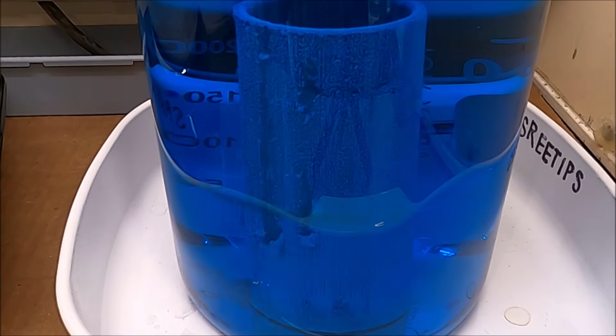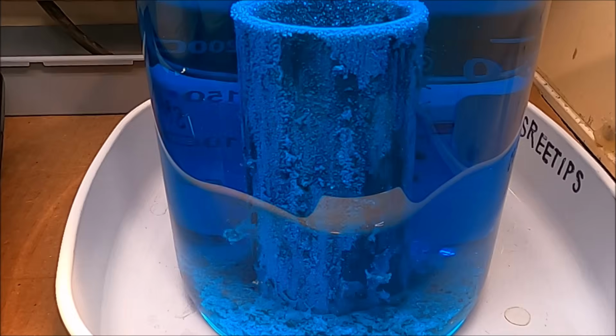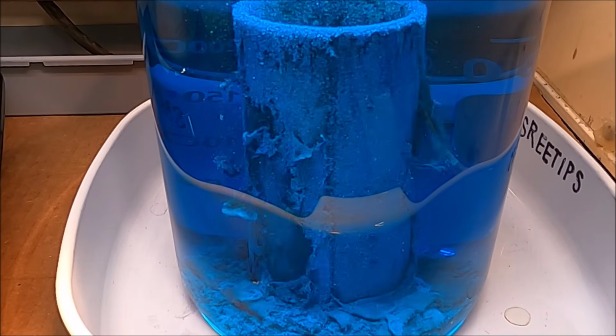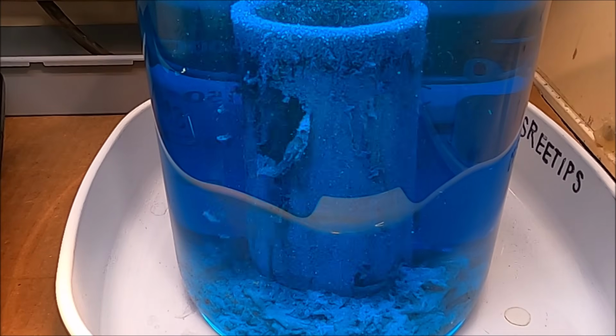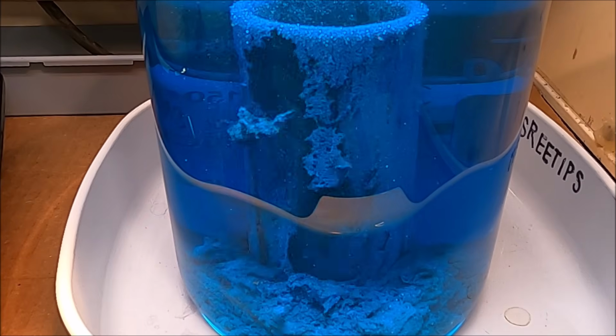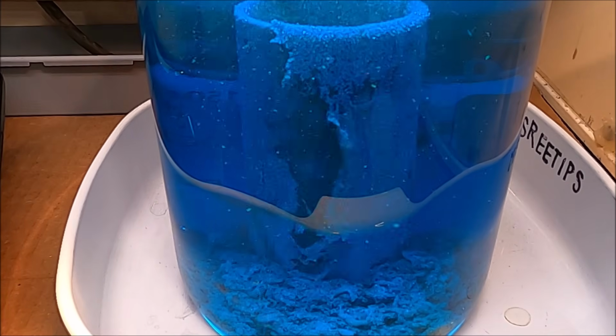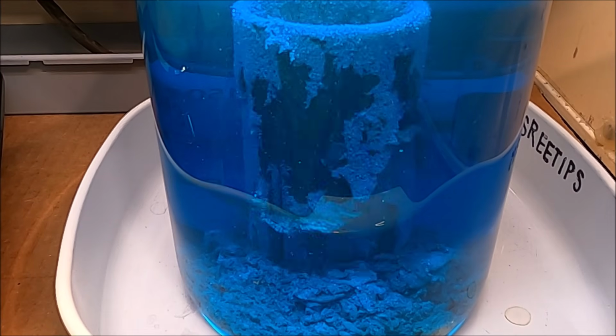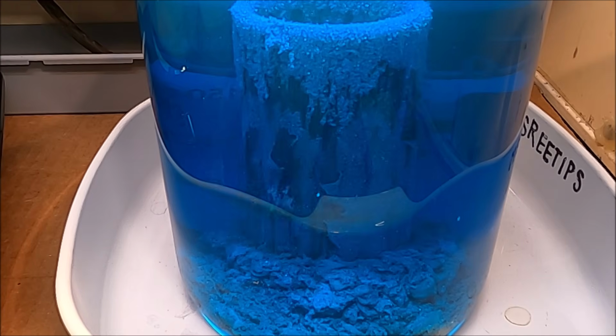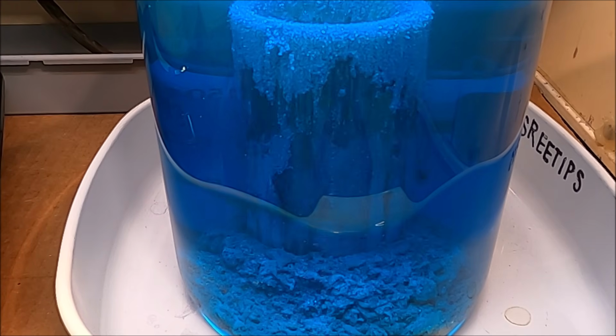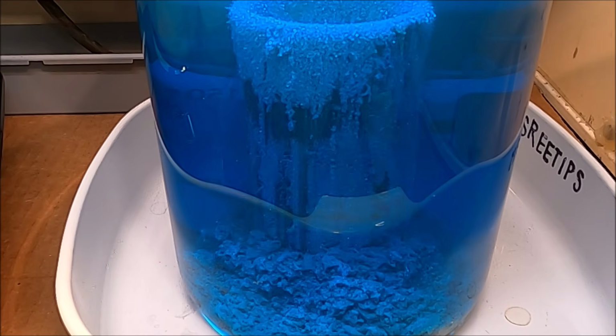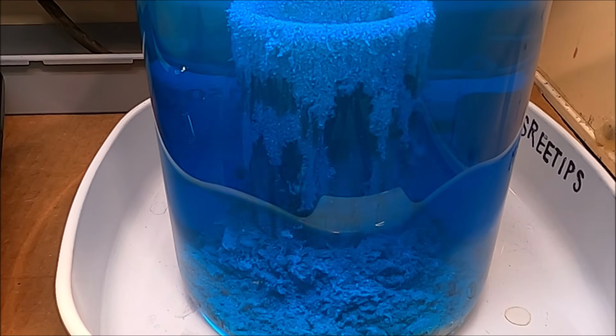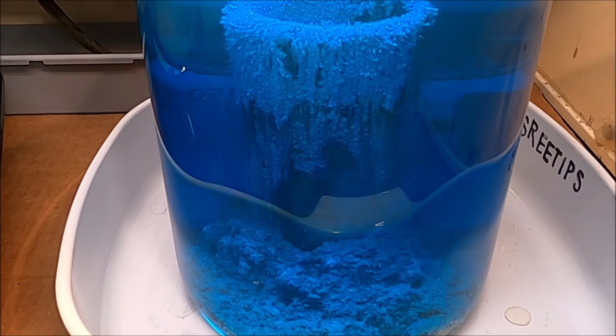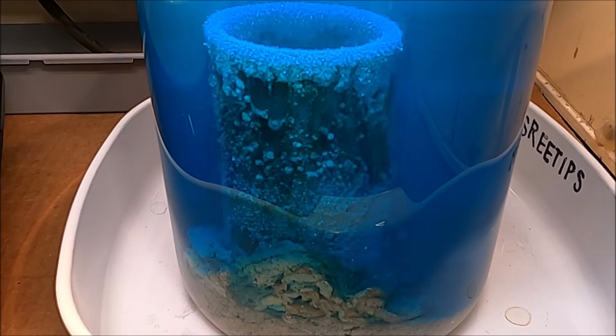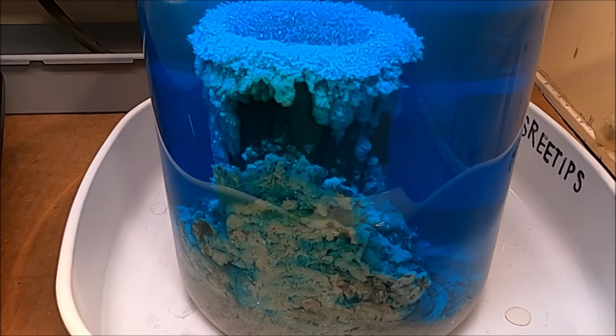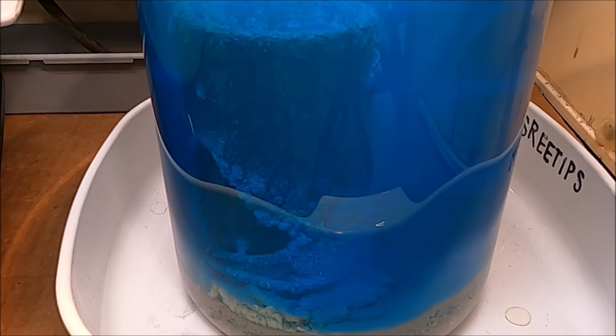This is the spent electrolyte from the silver cell. The silver cell has had 2 runs on this electrolyte, but as you can see, there's still silver in that solution. In accordance with the reactivity series of metals, copper, being a more reactive metal, will cement out a less reactive metal, in this case silver. The silver comes out of solution onto the copper, the copper goes into solution, the 2 metals trade places, and that silver coming out of solution on that piece of copper will be fairly high purity. We'll rinse all of the blue liquid off of it, and then we'll melt it into shot and run it back through the silver cell to form pure silver crystal.